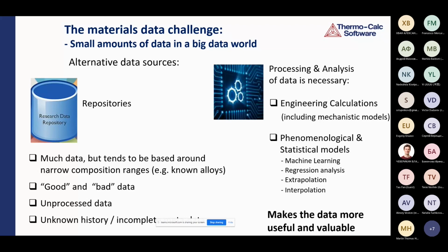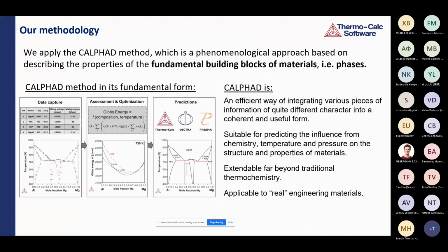So the methodology we are using for our tools is the so-called CALPHAD method, which is a phenomenological approach based on describing the properties of the fundamental building blocks of materials, the phases. So it's an efficient way of integrating various pieces of information of quite different character into coherent and useful form. You process the data you have and build up a model, so you actually describe the Gibbs energy of each individual phase and how that depends on composition, temperature, and pressure. And then you can extend far beyond traditional thermochemistry, and you can apply it to real engineering materials.